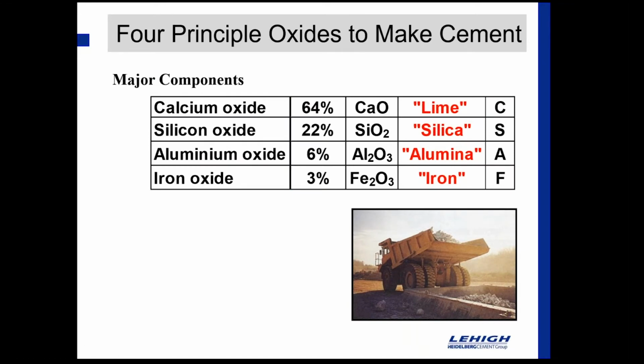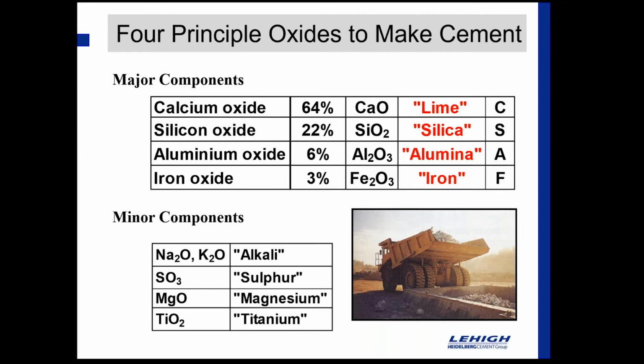So once we've got our limestone, really that is the key ingredient to move us toward understanding the four principal oxides that make up our cement. So from those oxides, there are four that are in particular needed. That's calcium oxide. We need it, and these are just rough numbers, 64%. Silicon oxide is about 22%. Aluminum oxide, somewhere in the neighborhood of 6%. Iron oxide, about 3%. So those would be the major components that are required before you can make cement. And then there are some minor components in the process. You have alkalis, sulfur, magnesium, and titanium.